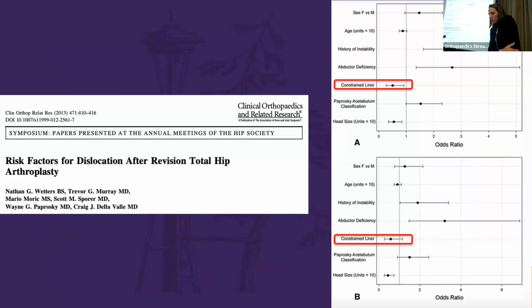I thought this was interesting. This paper is looking again at risk factors for dislocation after revision. The top panel, panel A, is the odds ratio for dislocation at 90 days follow-up, and panel B is odds ratio for dislocation at 1 year follow-up. And you can see, maybe although this is small, obviously, the constrained liners were protective against instability at 90 days with an odds ratio less than 1, and this was significant. But that lost significance at the 1 year follow-up, which I suspect reflects the fact that these work as intended until the stress, whether at the bone implant interface or cement liner interface, becomes too much if they're being relied on inappropriately, and then they begin to fail.